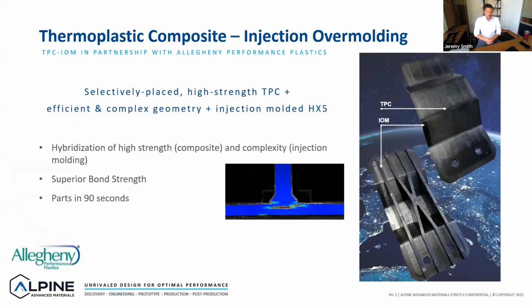We use the HX5 material to replace aluminum alloys. But to target stainless, titanium, and other high performance metal materials, we have developed a process with our partner Allegheny Performance Plastics called thermoplastic composite injection overmolding, a very brief and succinct title. We abbreviate it as TPC-IOM. Essentially, it's a hybrid solution of thermoplastic materials and high performance, high tensile strength unidirectional tapes. What you see in the image on the right is a combination of about 10 to 12 layers of a high performance unidirectional PEEK material overmolded with our HX5 material.